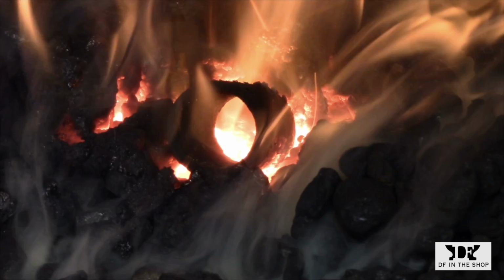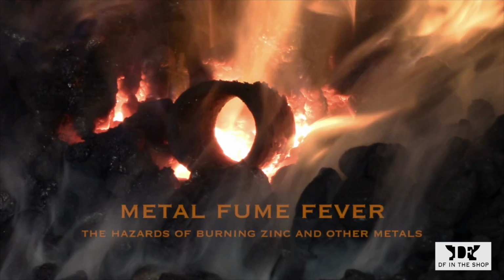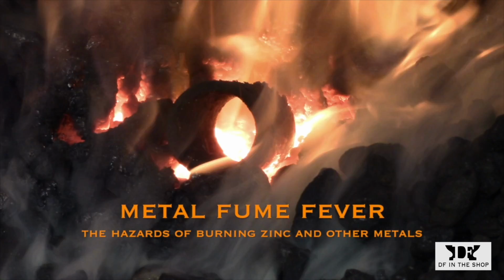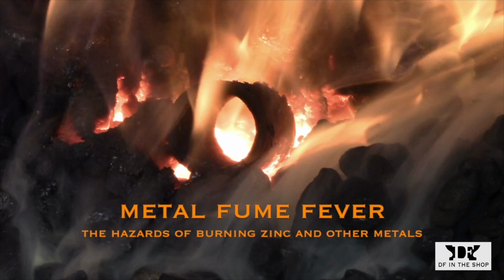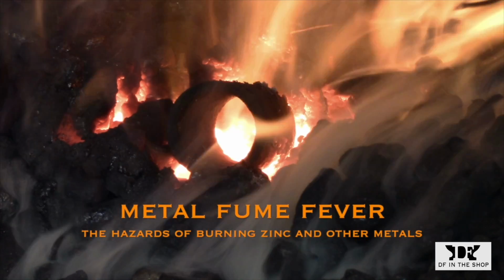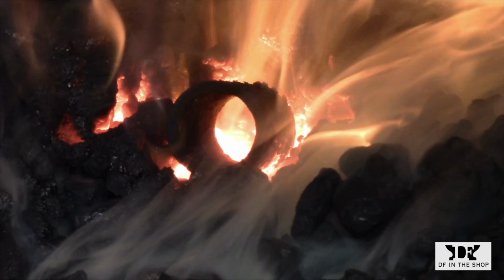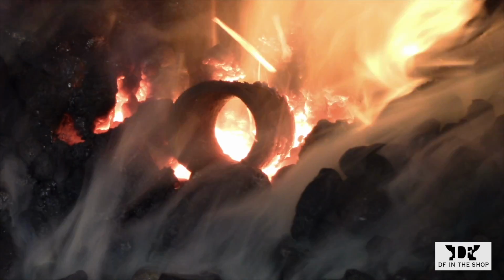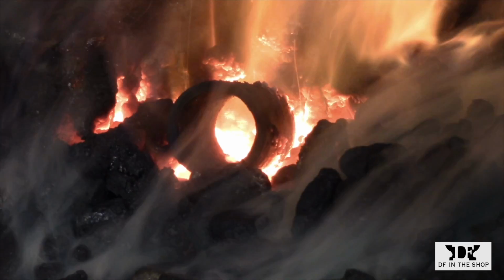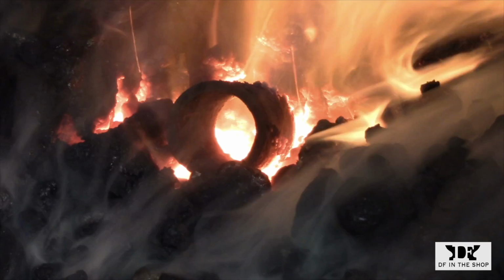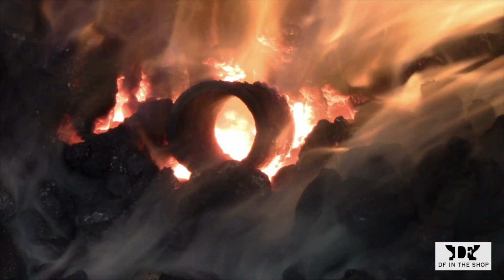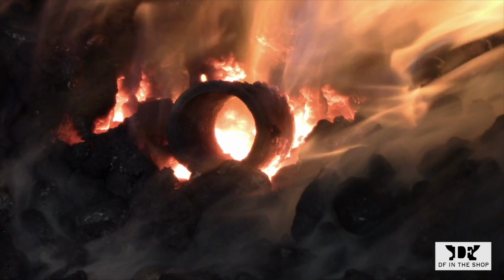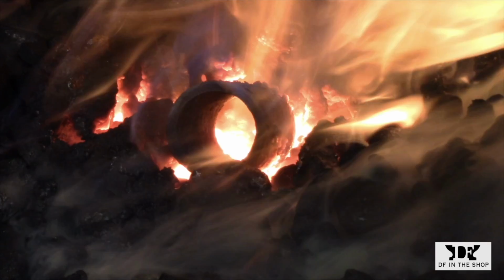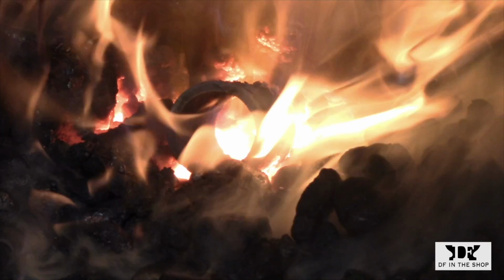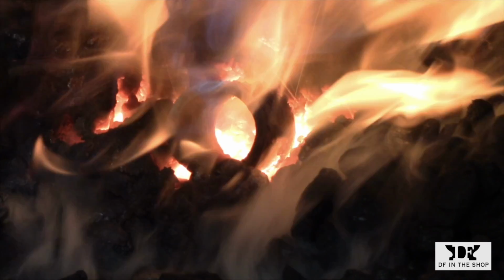What I'm doing here is very dangerous. I have a piece of galvanized pipe in the forge, and in a moment you're going to see the zinc oxide from that galvanized coating turn into a gas. Prolonged exposure to this gas will definitely make you very sick, and in extreme cases it'll kill you. The condition is called metal fume fever, and it's caused by breathing in the gas produced by burning certain metals.